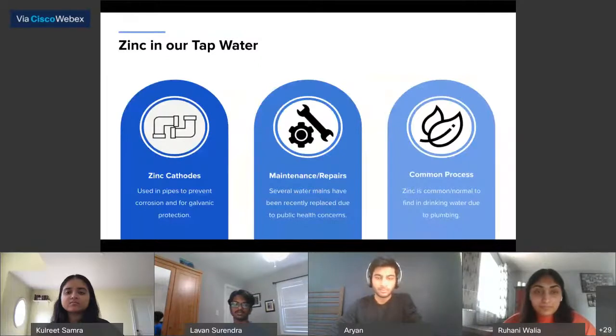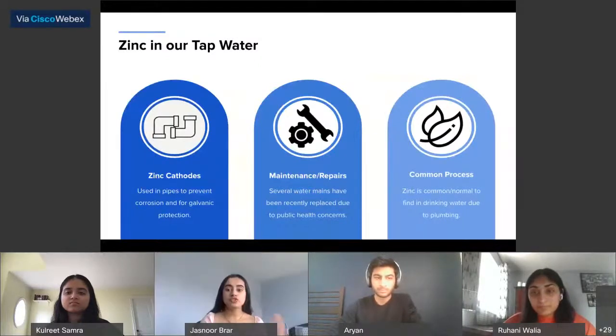The presence of zinc in tap samples could be from the structure and elements used to build these pipes. In fact, zinc cathodes are used for galvanic prevention in these pipes to prevent corrosion and for grounding. Hamilton had the highest amount of zinc in tap water relative to the 2 other regions, and this is likely because of recent piping changes or maintenance that was done.